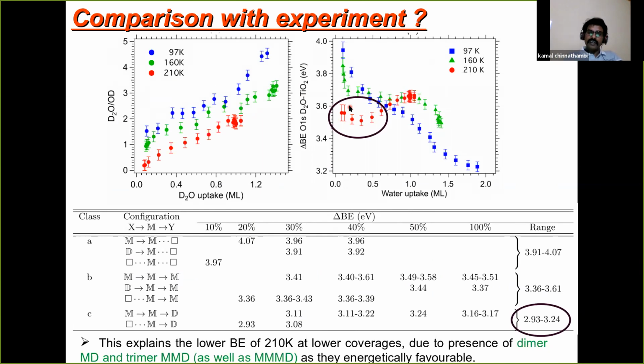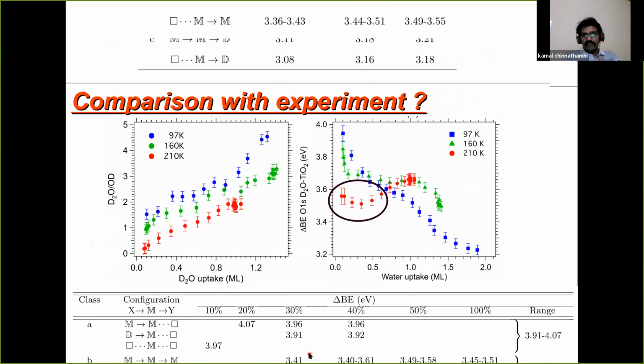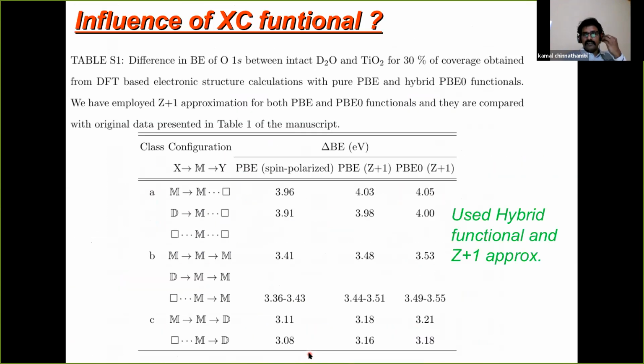Once you have more dissociated molecules, a dissociated molecule as an acceptor to any neutral molecule will give you a very, very low binding energy. That explains that at 210 degree, we have more cases of dimers or trimers, like neutral then dissociated, this kind of combination. The only important thing is that you should have a D as an acceptor. Once you have that, you will get this kind of signal. So we know what kind of molecular species are involved in the initial stage of the growth.